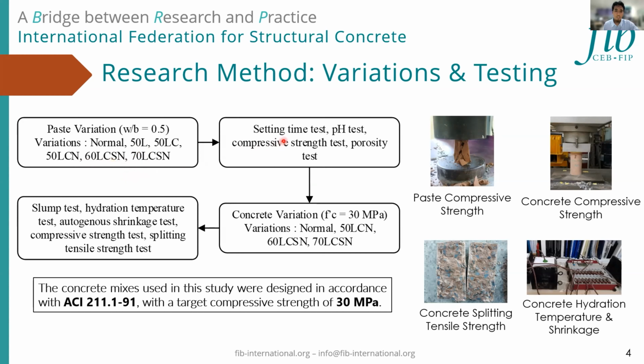The tests carried out were setting time test, pH test, compressive strength test, and porosity test. After that, 3 variations have been selected based on 28 days base compressive strength to make them into concrete specimens. The tests carried out were setting time test, slump test, hydration temperature test, autogenous shrinkage test, compressive strength test, and splitting tensile strength test.